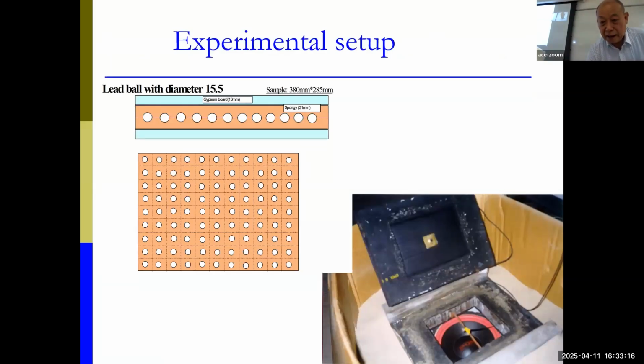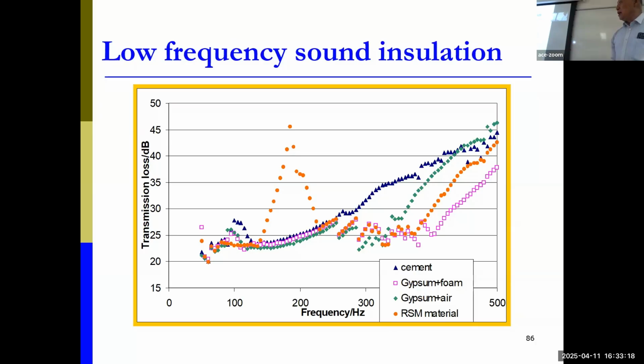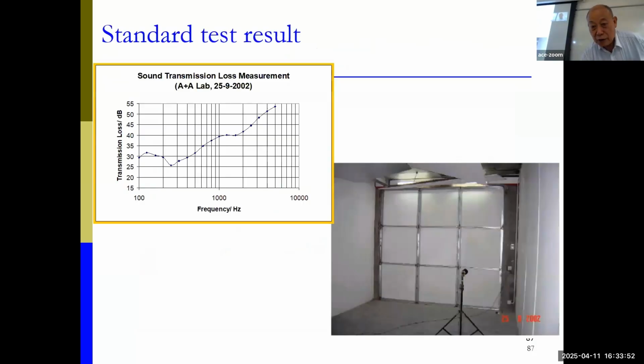So we did the basic experiment, and you can see a very good verification. We tested many materials: concrete, gypsum board, some composites, and also our material called RSM. Between 140 and 240 hertz, which is very low frequency, we have a peak of about 45 dB, but the normal materials are less than 25. That means there is a 100 times difference in blocking this low frequency.